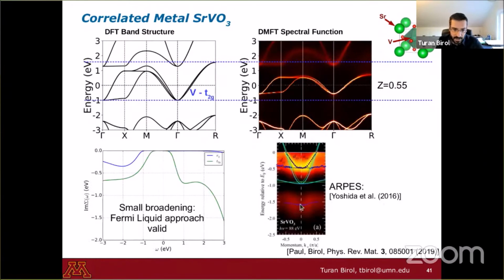And when you compare this with the experiment, two things are apparent. One, if you are an expert in this field, I guess I should say that the Fermi liquid approach is still valid because the imaginary part of the self-energy goes to zero right at the Fermi level. So right at the Fermi level, things are perfectly sharp. But when you compare with the experiment like ARPES, angle-resolved photoelectron spectroscopy, then the bandwidth of DMFT matches much better than that of DFT.